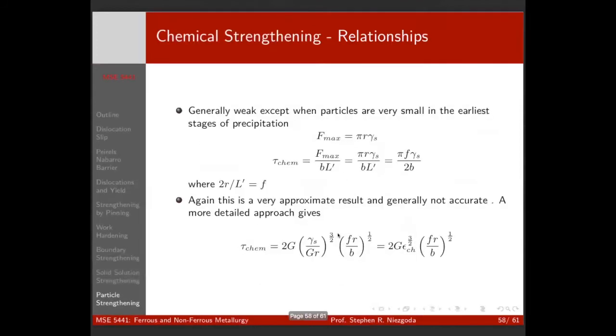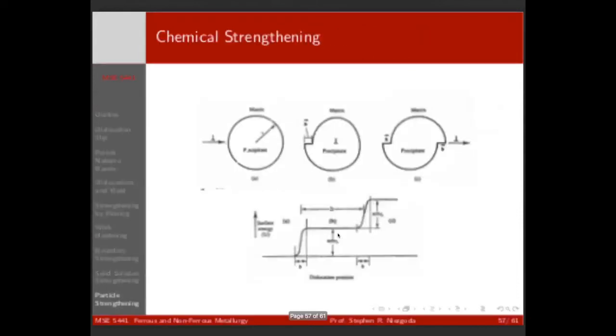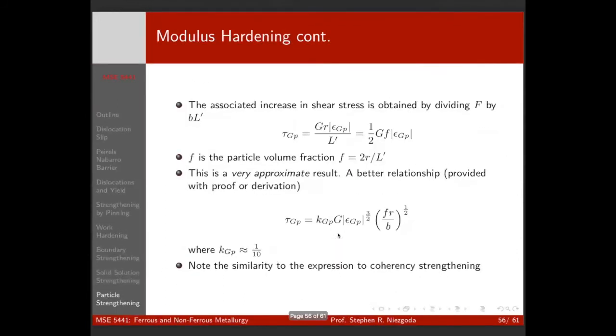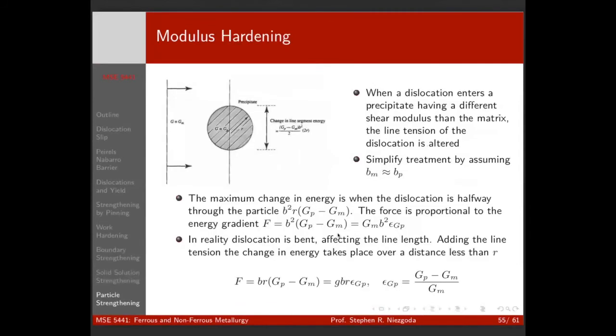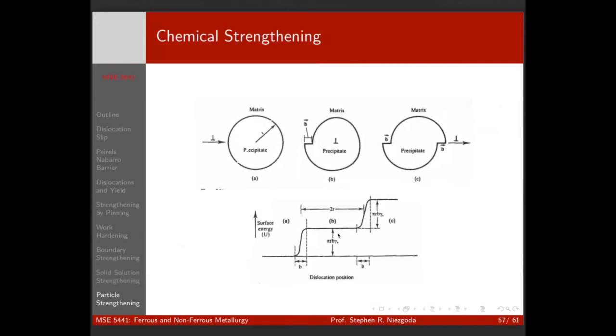If the interface is not coherent. For modulus hardening. Yes. So if it's incoherent, it will generally be much smaller than what you have to pay to get through an incoherent interface. So you can generally neglect it then because it will just be smaller. Right, but by incoherent, you really can't cut through, because the dislocation has been changed by passing through the interface. Right, it's not the same dislocation in the particle as it is on the outside. Right, so it's not really the same thing. Right. For this, we just want to go over general effects, so we have a framework to talk about these things, right?